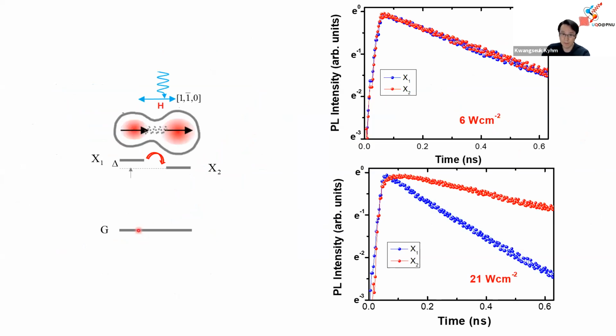We also studied time-resolved photoluminescence because wave function extent is also associated with oscillator strength. So the larger the wave function, the larger the oscillator strength, and that gives a faster decay time, if it's the case of radiative decay time. And when excitations are small, the difference is small, but as you increase the power, high energy X1 becomes fast, but X2 slows down. Okay, so the wave function extent becomes modified through the dipole interaction.